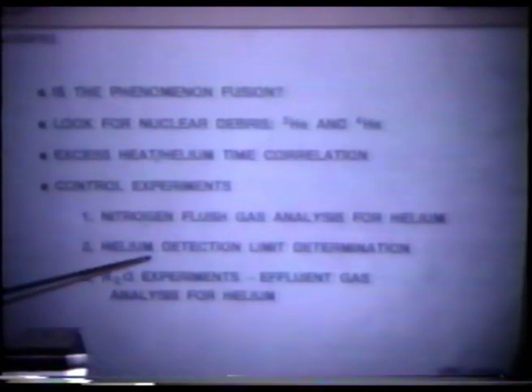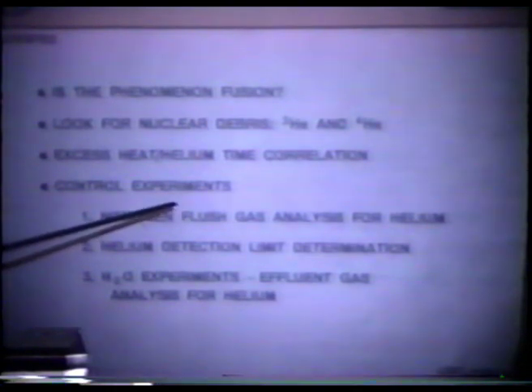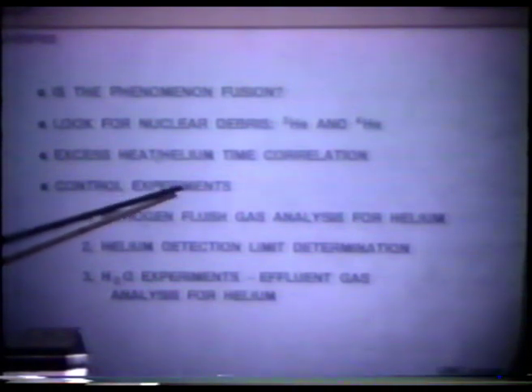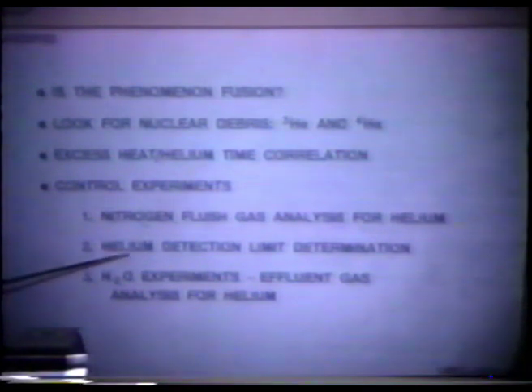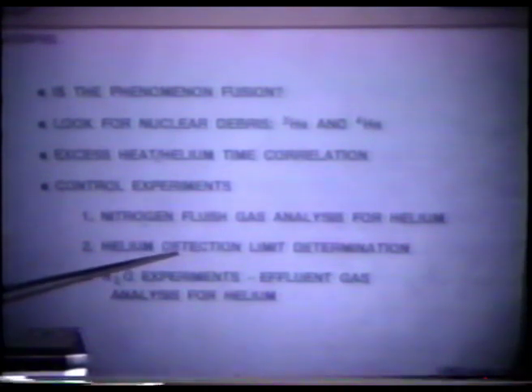And we realized we'd have to run control experiments. We found nitrogen flush gas was a good gas to use because we could not detect helium in the boil-off nitrogen. We tried argon first. That was terrible. A lot of helium in the argon. But the boil-off nitrogen, we could not detect helium in that, so we used that for a flush gas. And we purposely added a little bit of air to determine our helium detection limit. And later on, we ran H2O experiments exactly the same way to see what would happen in that case as a control.